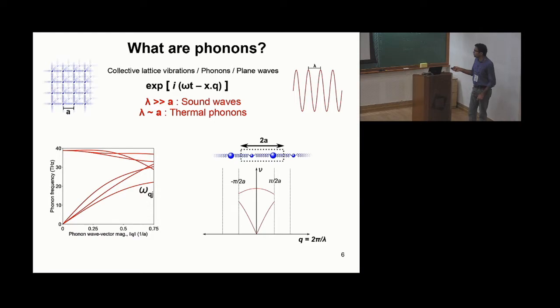You can make this problem slightly more complicated by adding one more atom to the unit cell with a different mass, and because now you have additional degrees of freedom, you get another branch of the dispersion. The low frequency branch is typically called the acoustic phonon because it's lower in frequency, and the higher one is called the optic phonon. This is the typical dispersion you get for a one-dimensional spring. If you have 3 dimensions as in real materials, you have 3 acoustic phonons and 3 optic phonons. This is basically the fundamental understanding of what phonons are in a material.